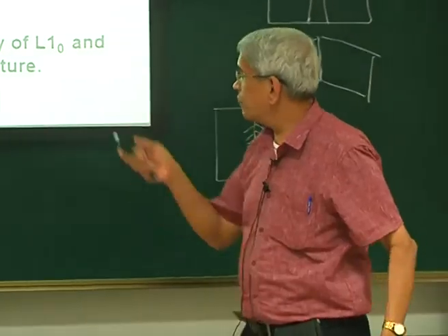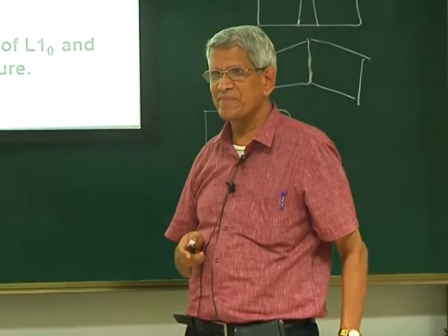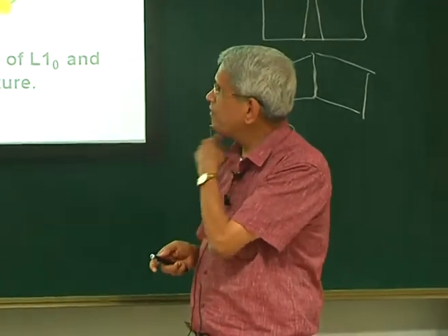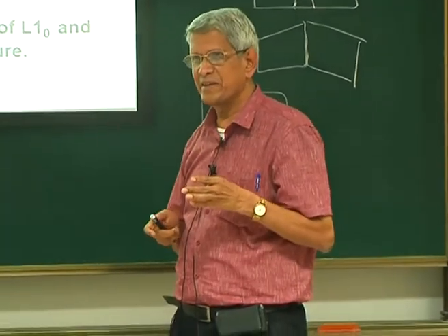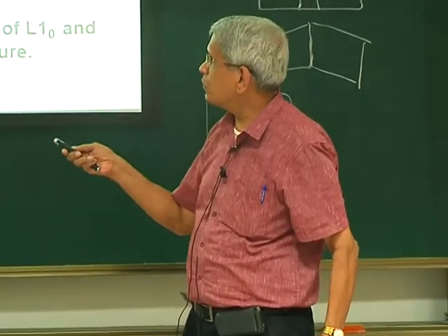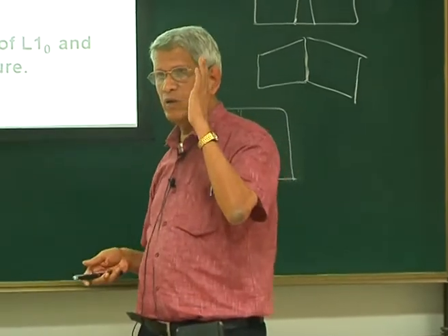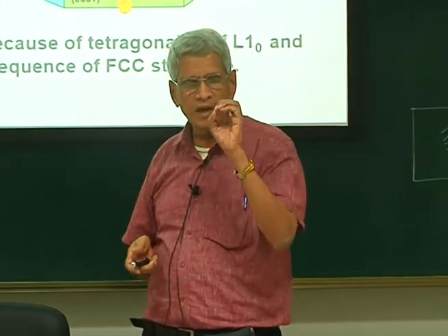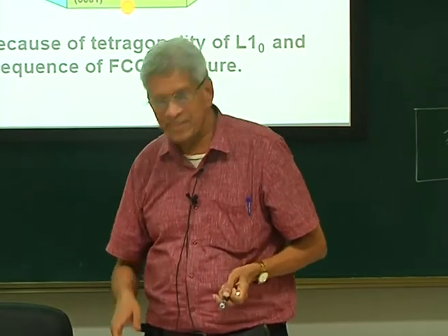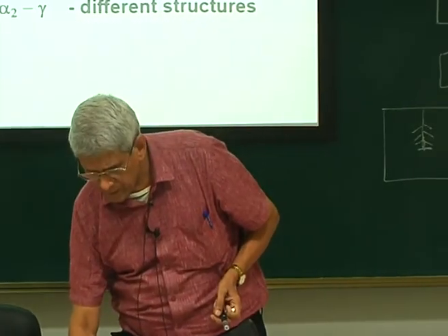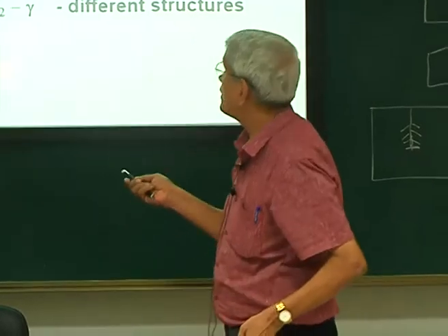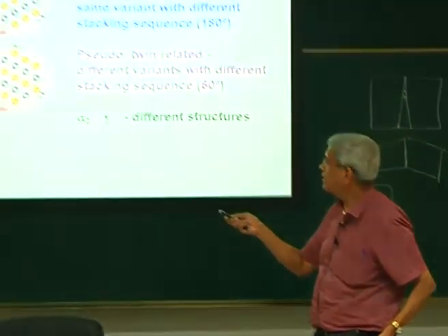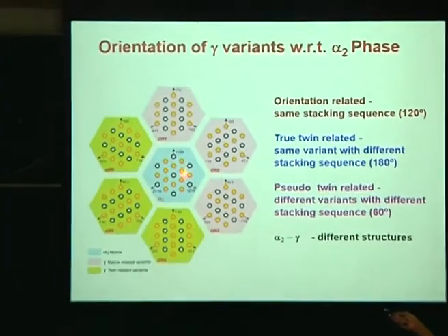And here what happens when it is an ordered one, okay. Here we can have essentially 6 variants. That is because in this particular lattice, along one-on-one plane, if we look at it, the threefold symmetry is lost. So, this is what is being shown here. This is for an ordered HCP, but you assume that this is disordered, all will be of the yellow color.